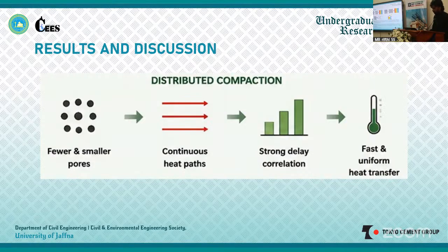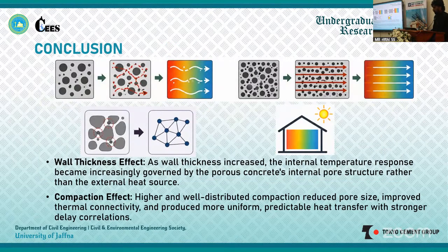And finally, to conclude, this study found two important observations. First, as the wall thickness increases, the internal temperature response becomes more dependent on the internal pore structure than the external heat source. And second, higher and well-distributed compaction reduces pore size, improves thermal connectivity, and produces more predictable heat transfer with strong delay correlation. And thank you.